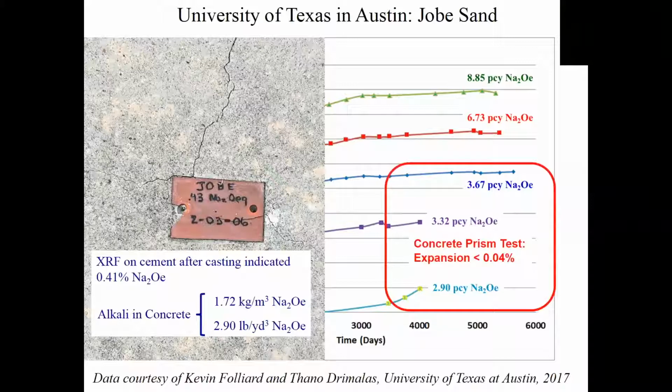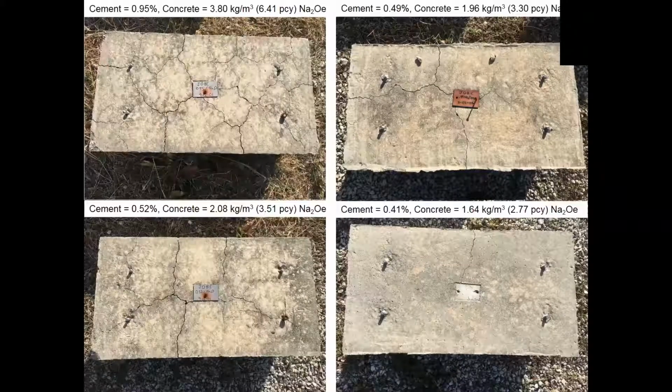What's interesting here is that 3 of those concrete mixes do not expand in our concrete prism test. They all expand out in the field, but not in the concrete prism test. So this data has all been provided to me by Kevin Folliard and Thano Drimalas, University of Texas, and Thano just sent me these 4 photographs this morning to include.